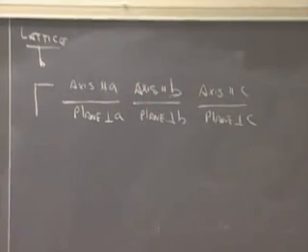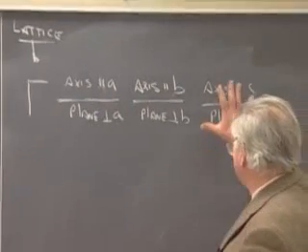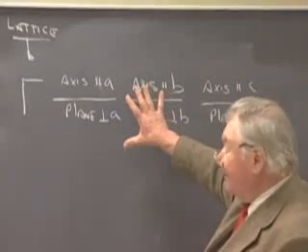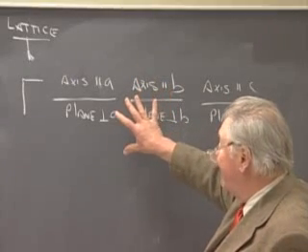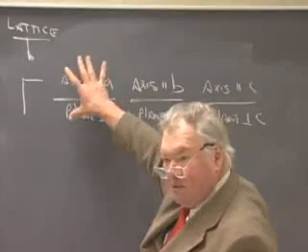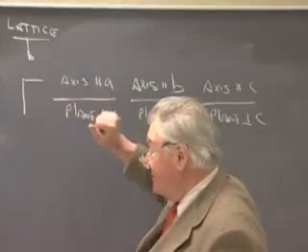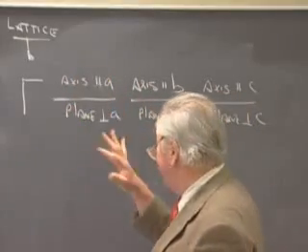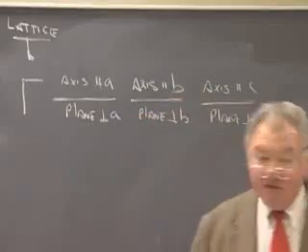Okay, so this is a convention for orthorhombic, and again, this is the only crystal system where conventions that elaborate are necessary. Were this tetragonal, 4 or 4 over m would always come first because that's the direction of C. So even the order of the symmetry elements is different.